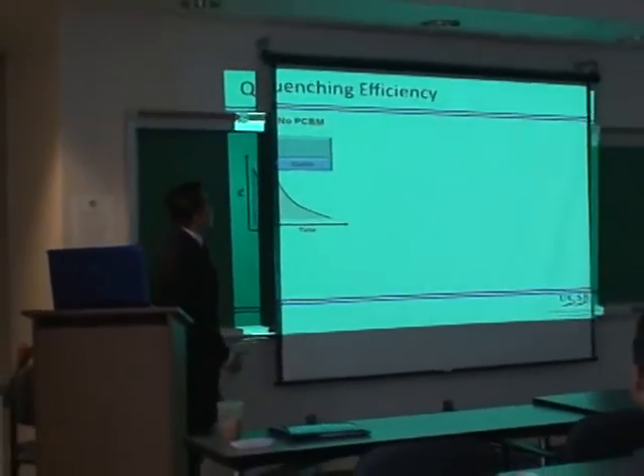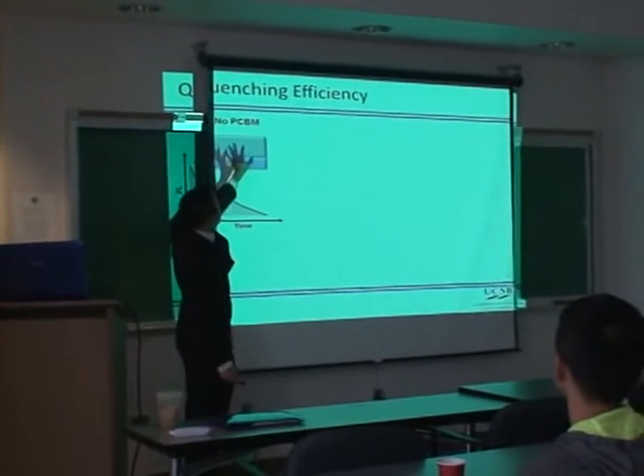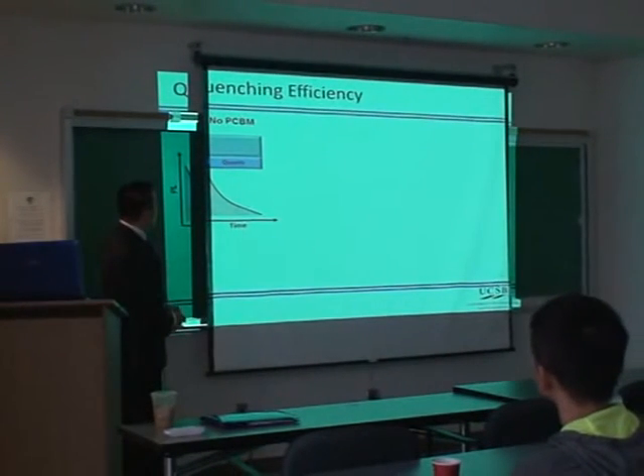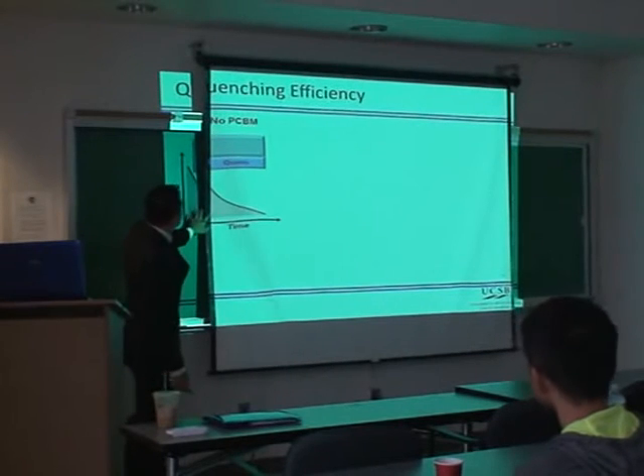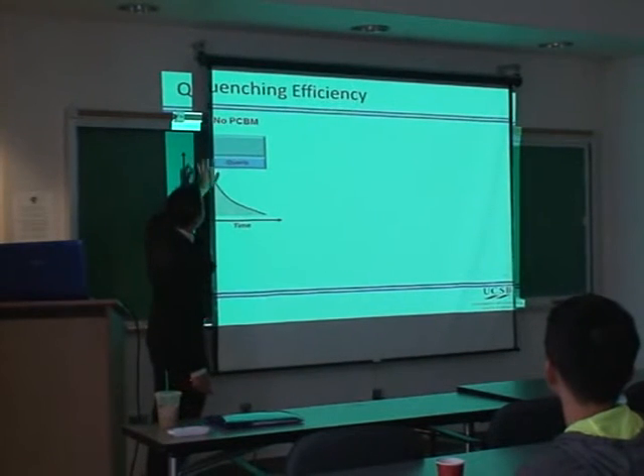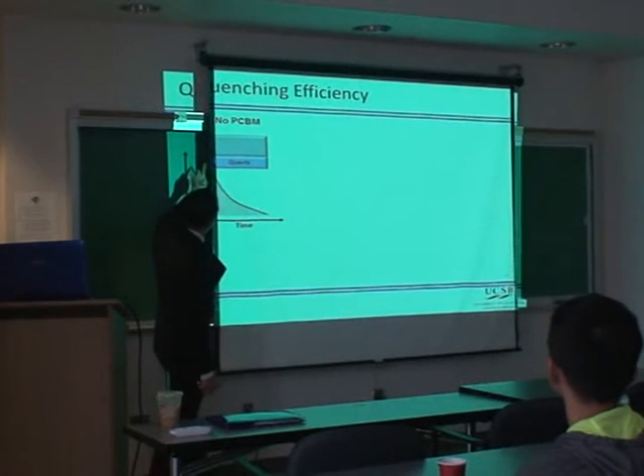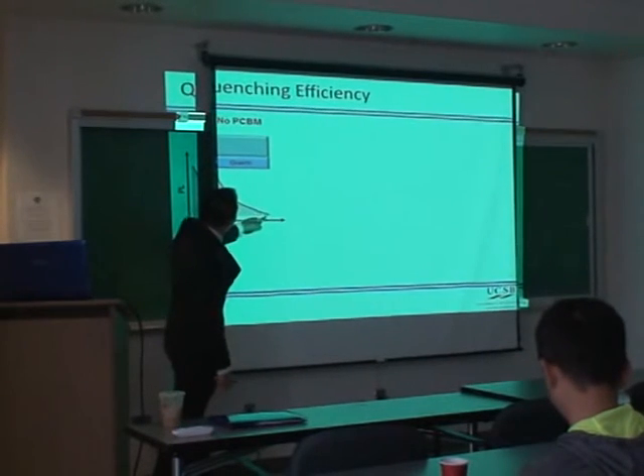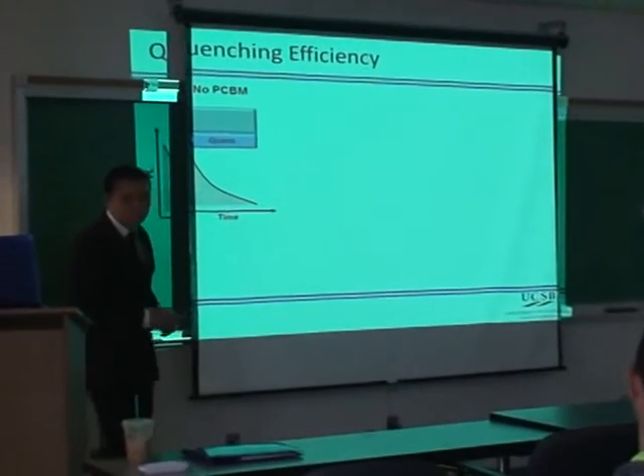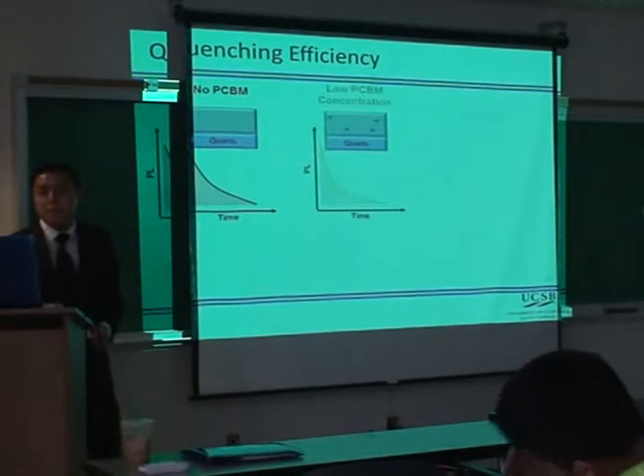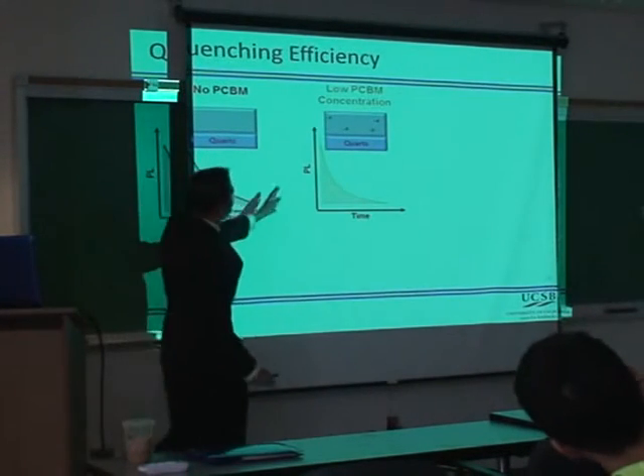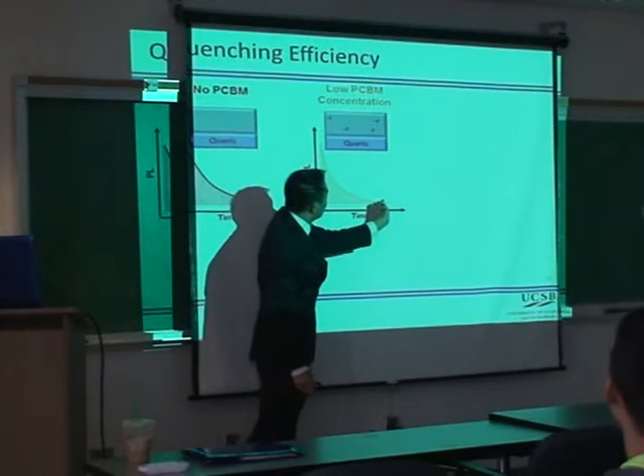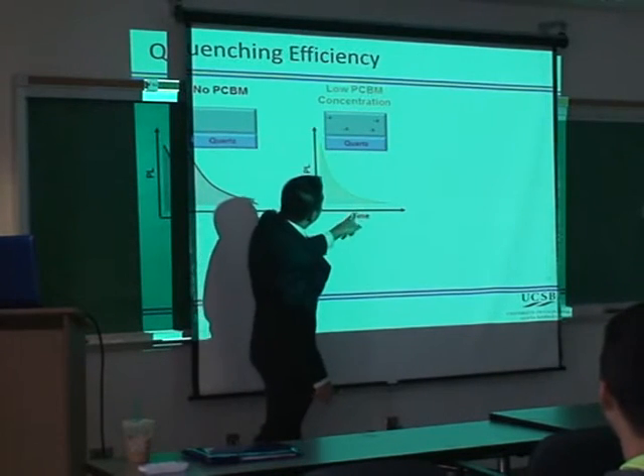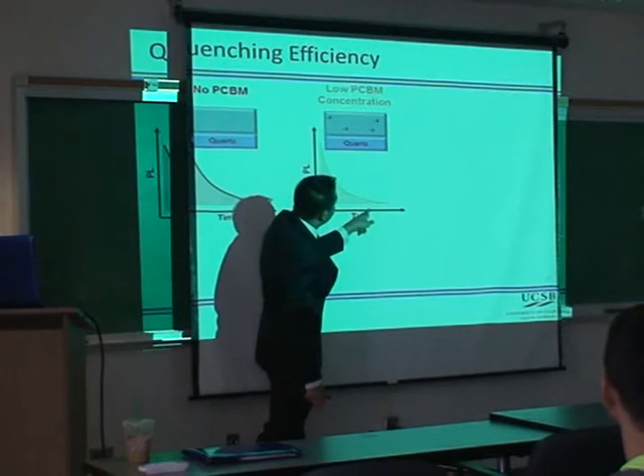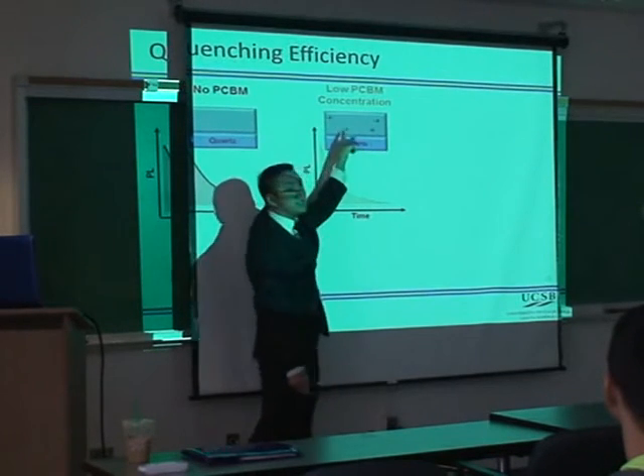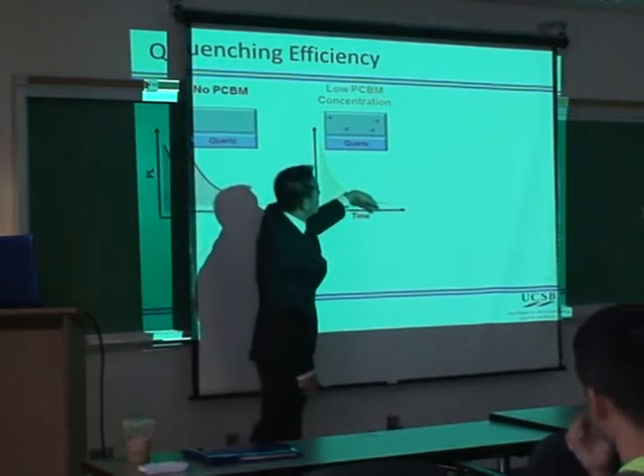So now the question is, how do we calculate the quenching efficiency of this curve? Well, let's first look at the plot for a film without any PCBM. Like I mentioned earlier, we'll have this exponential decay curve, and we'll have an area underneath. But if we were to add some PCBM, what we see is that there's a more rapid decay of the excitons, basically because there's a less likelihood of longer-lived excitons because they're more likely now to reach a quencher. So therefore, we cut down the exciton lifetime.